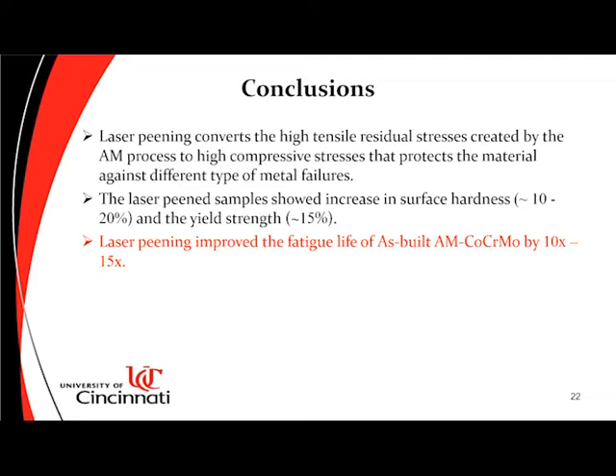So in conclusion, we say laser shock peening converts the high tensile residual stresses that are created from the AM process to compressive stresses that protect the material against different types of failures. And also, the laser peened sample showed an increase in hardness of about 10 to 20% and a yield strength of about 15%. And more importantly, the laser peening improved the fatigue life by about 10 to 15 times.